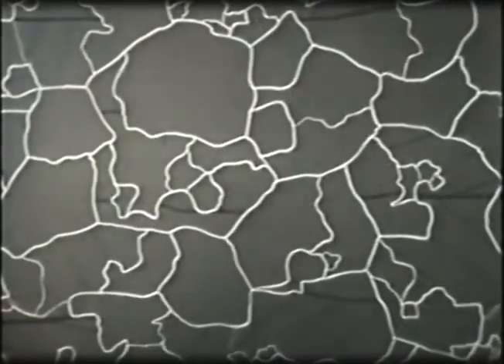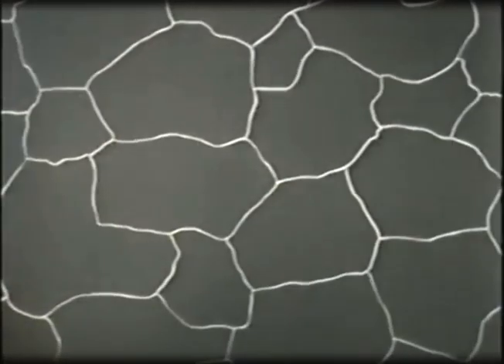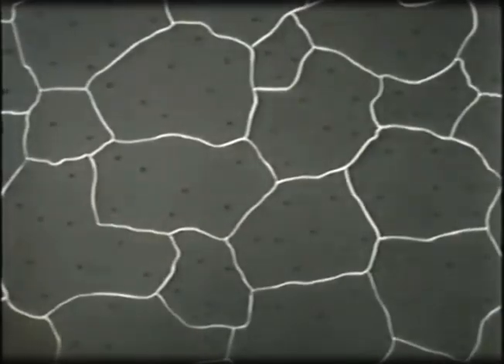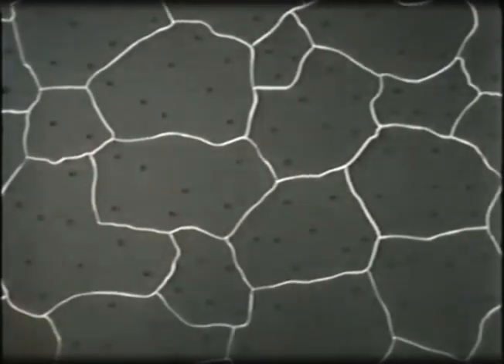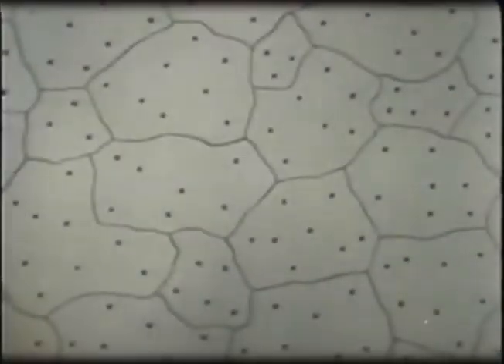The first internal change in the partial annealing is the relief of the cold work stressed grains and the recrystallization of the metal into new stress-free grains. The second change, resulting in partial removal of the effects of heat treatment, is the partial precipitation of the CuAl2 particles out of solution throughout the newly formed grain. The quench prevents this precipitation from becoming complete.